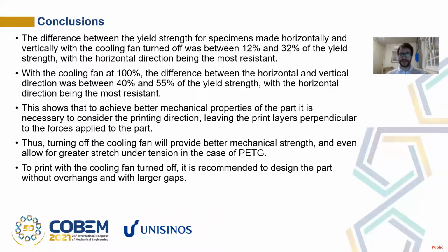So it shows that to achieve better mechanical properties, it is necessary to consider the printing direction, leaving print layers perpendicular to the force applied, and turning off the cooling fan will provide better mechanical strength and even allow for greater stretch under tension in the case of the PETG.